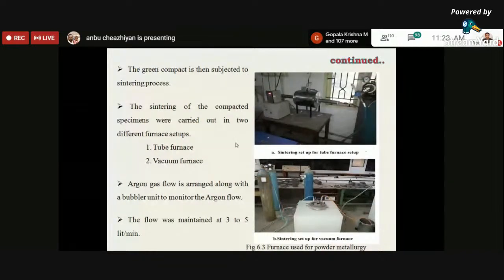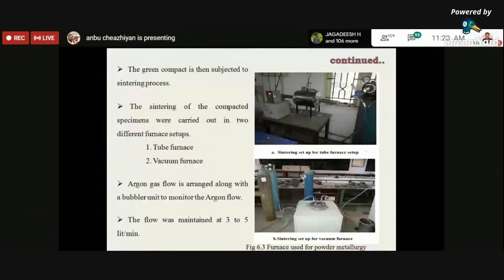The green compact is subjected to the sintering process. To prevent oxidation and excess burning, we are sending argon gas through it. This is the setup that we are using, and we have a bubbler unit to control the pressure of the gas flow. This is a tubular furnace, with a boat-like structure.